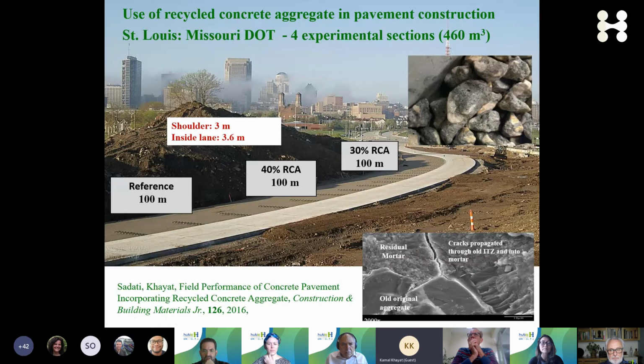We've been also using quite a bit of recycled concrete aggregate. This is some recycled concrete coming from our airport in St. Louis that was put to use as a test bed with the city of St. Louis and the Department of Transportation of Missouri to construct the test beds of concrete pavement with 30% recycled concrete aggregate. This is coarse aggregates, and 40%, and also another 40% using a different procedure for mixture design. So I'll be happy to report on these findings in the future.